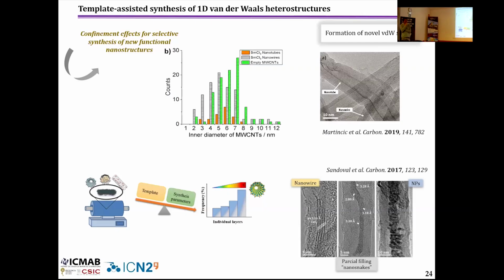We can tune the flow of ammonia, and this way, in principle, you can tune also the temperature. So by increasing temperature, you can modulate the amount of nitrogen that you introduce inside. So it's a very simple solid-gas reaction inside the tubes. The powder is in contact with gas.